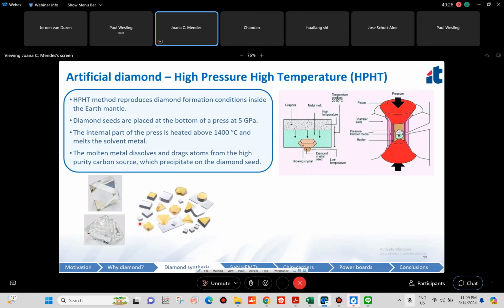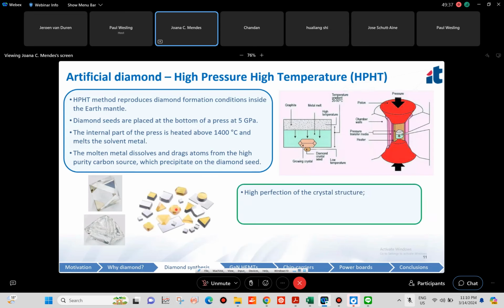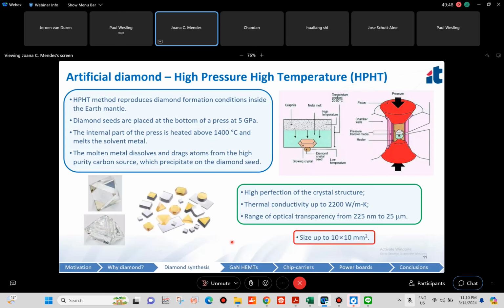And you can see that they come basically in two colors. So you have the transparent one, without color, and you have the yellow diamond, simply meaning that it is nitrogen rich. And then these crystals are very, very perfect. They have high thermal conductivity, up to 2200 watt per meter Kelvin, and they are optically transparent, but their size is limited to 10 by 10 millimeter square, typically.